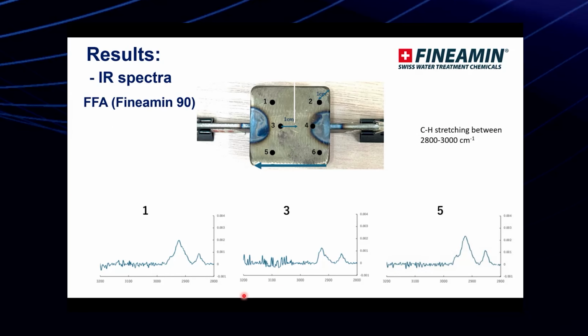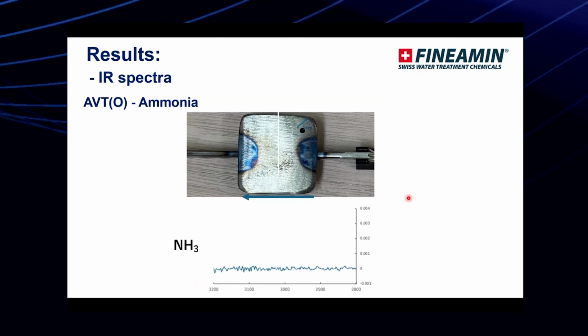Just for your information, if you remember, we swabbed with methanol on half of the steel plates, so points 2, 4, and 6 were already swabbed by methanol, so there is supposedly nothing inside. So we focused on the other part, points 1, 3, and 5, and we could see a clear indication of the carbon hydrogen vibrational bonding. Here we could see the stretching of the C-H bond between 2,800 and 3,000 per centimeter wavenumber. So you can see we have a clear indication of absorption, and if you compare it with the one with ammonia, there is nothing.